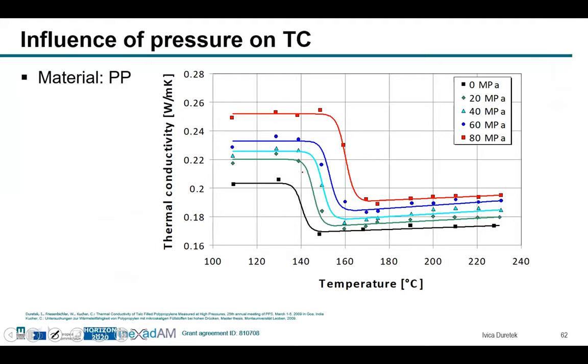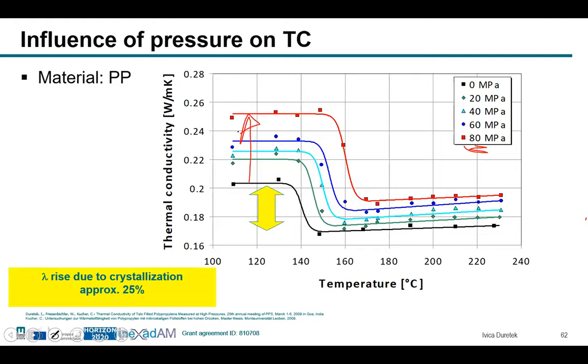In this slide, you can see the influence of the pressure on the thermal conductivity. These measurements were done between 100 and approximately 230 degrees on polypropylene. And the pressure was changed from atmospheric pressure up to 80 megapascal. The increase of the thermal conductivity is very clear. In the solid state, due to the crystallization, we have an increase of thermal conductivity of approximately 25%.